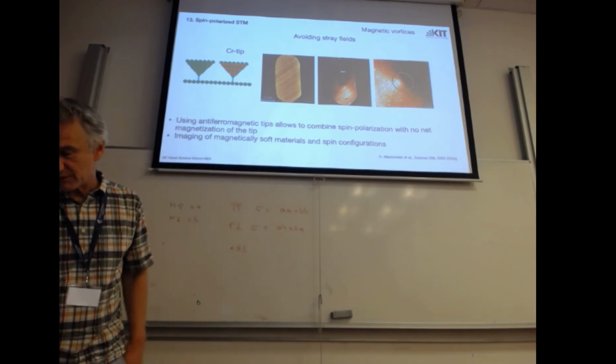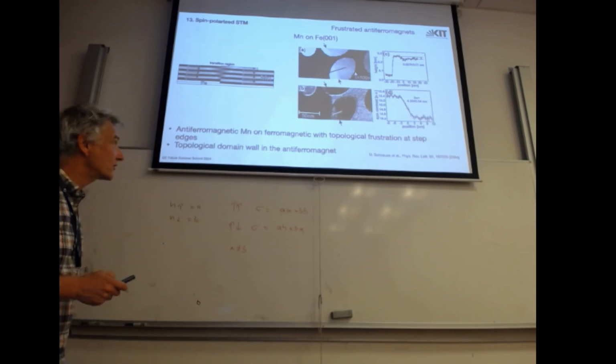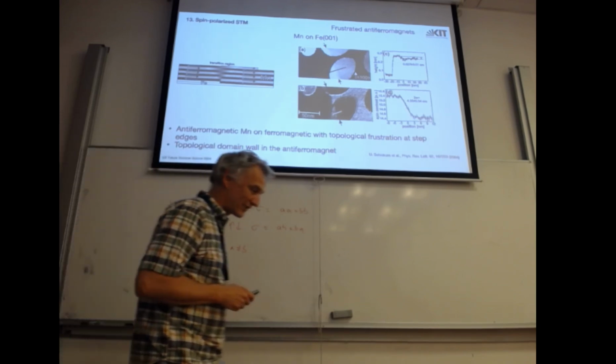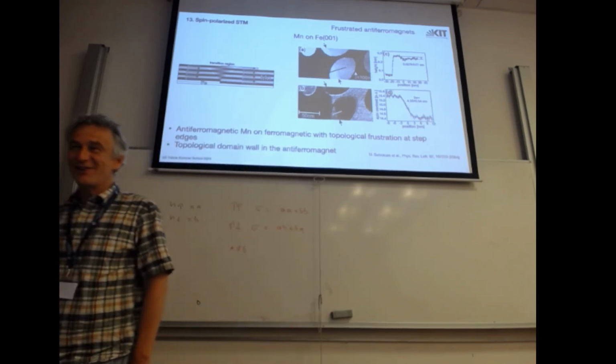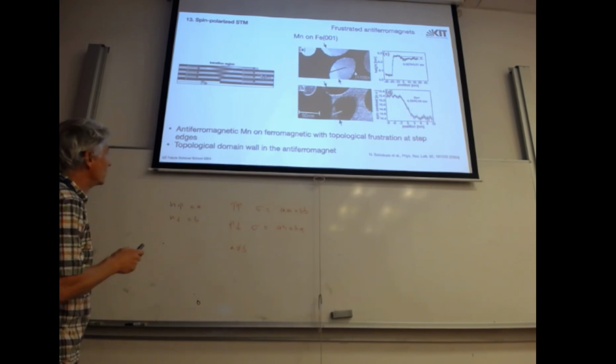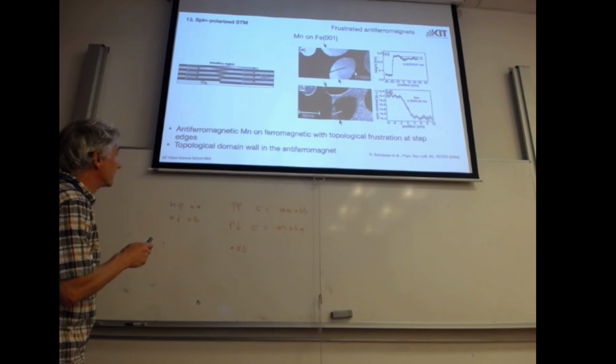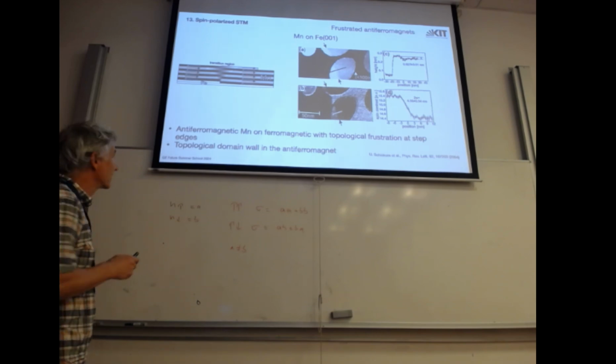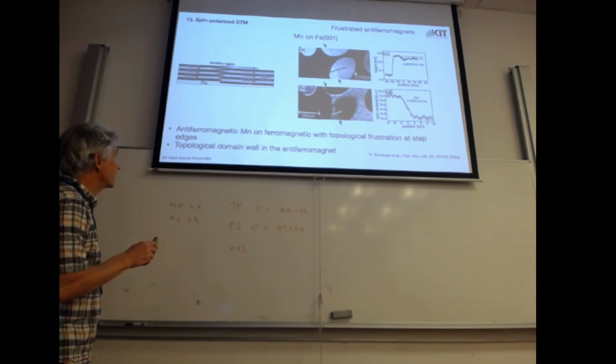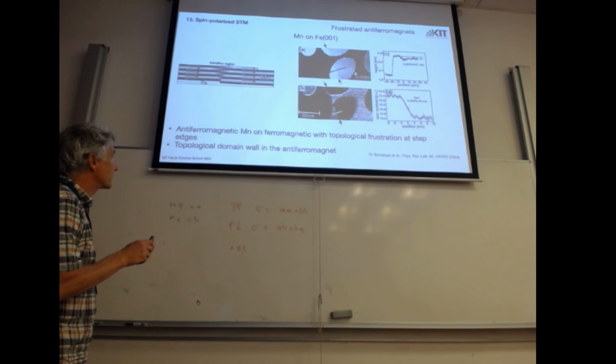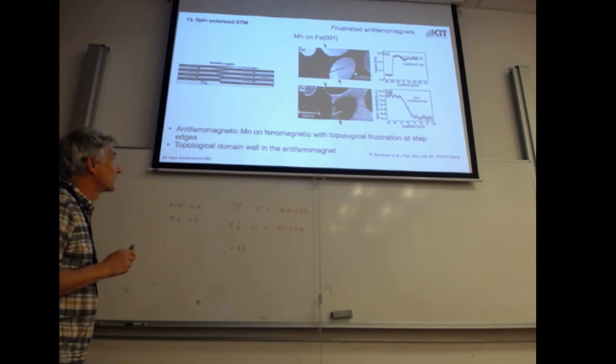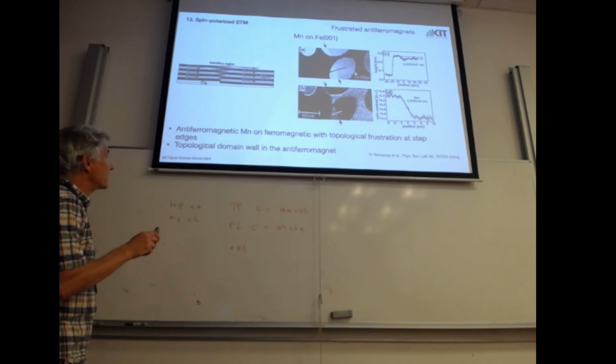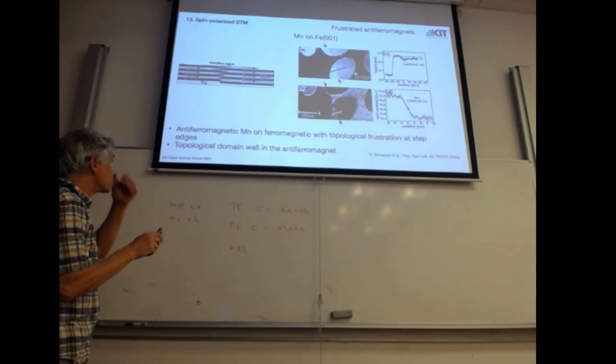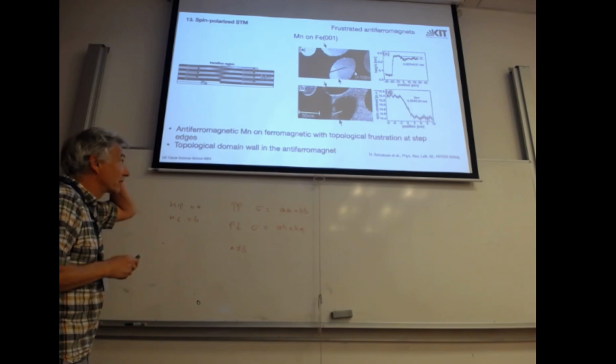It's like STM. We also did something, since we had talked about frustration, I switch to frustration now. We grew samples like this. This is an antiferromagnet, manganese, on iron. It's a layer-wise antiferromagnet, and let's say manganese couples ferromagnetically to iron. So that means if I see a step edge, I go from an even to an odd number of layers on top of the iron, I should see a contrast, spin contrast.